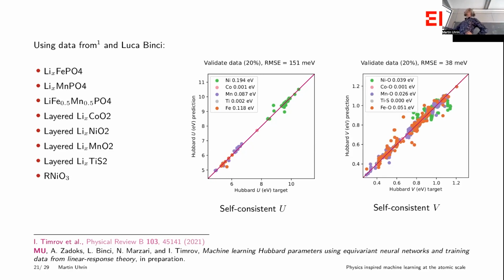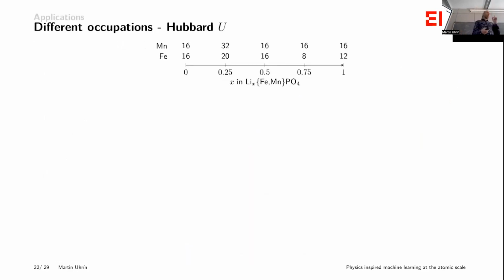The story is pretty similar for V, except the spread is slightly worse, but it's still very much good enough for what we need. And keep in mind, yes, it takes quite some time to generate this data. These aren't cheap calculations, but then to run these is now of the order of a millisecond to get your answer, and then you run your calculations. So we've thrown away that cost of 100, but only if we can trust the model, right? Because of course we'll be going to things that it's never seen before. So can it extrapolate beyond the training data that it's seen?